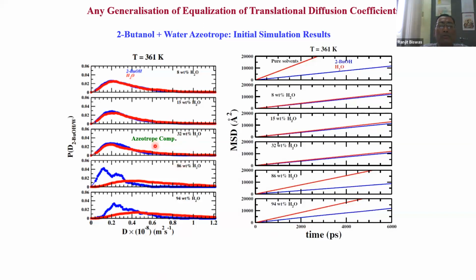And exactly, this is for the 2-butanol water azeotrope. The azeotropic temperature is 361 K. And what we see here is that at 32%, which is the azeotropic composition, we see the equalization of the distribution itself. So this is giving us an initial clue that probably these are a unique dynamical signature. Then the opposite test should be done: pick a system, maybe propanol water or methanol water, and follow their transport coefficients and see whether you see it or you don't. If you don't see it, then what we are getting at would be bolstered.